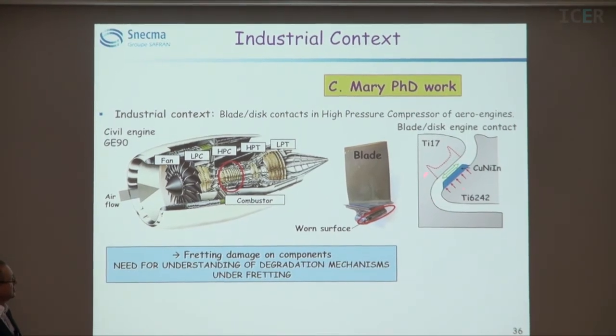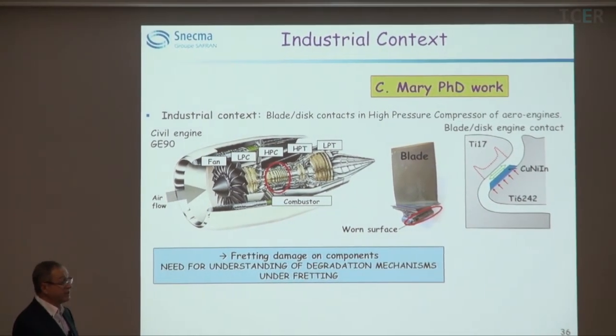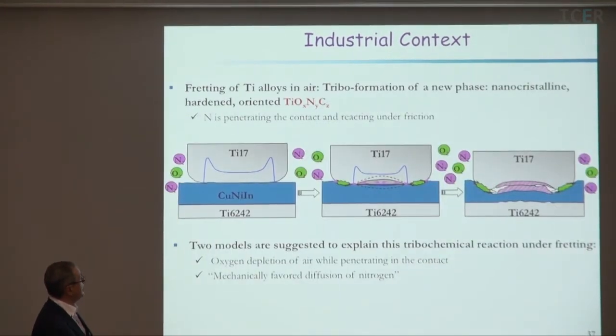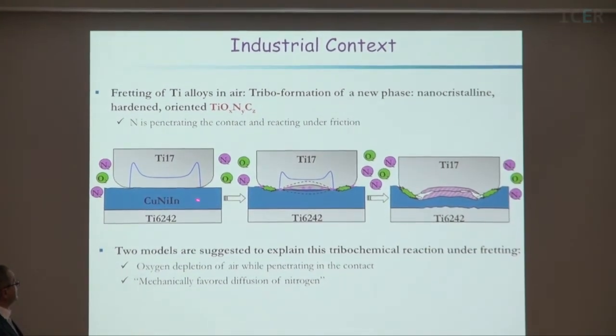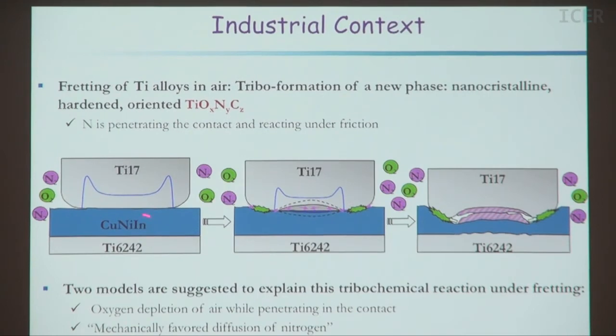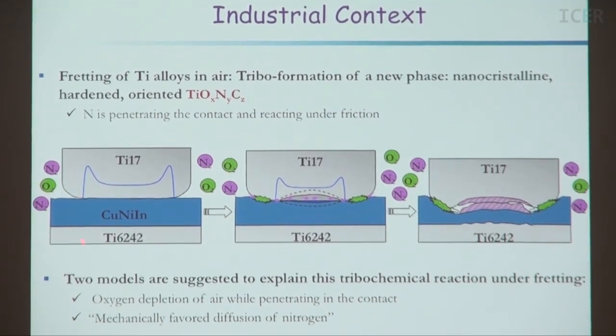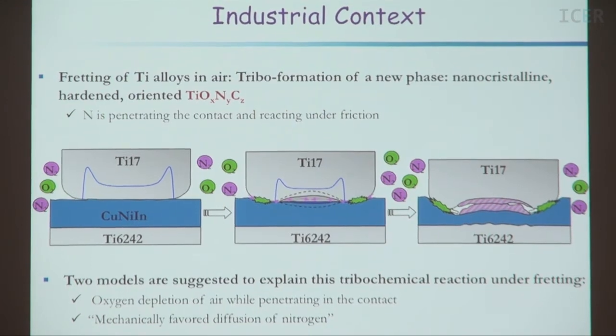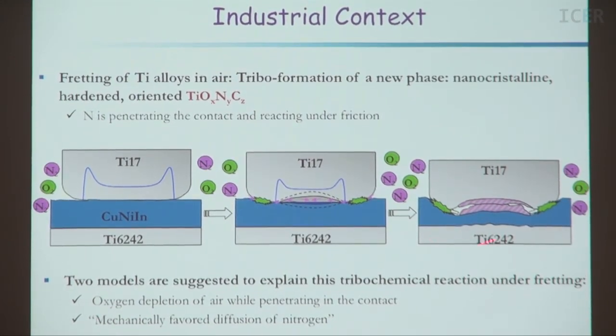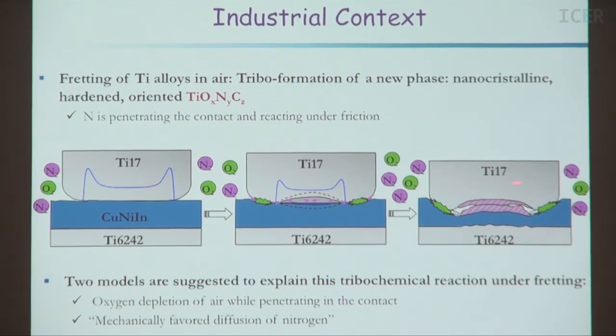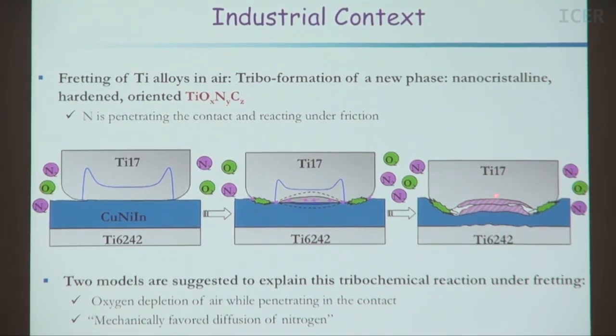So this is working in air, of course, in humid air sometimes. If we look at what happened, typically we are with titanium alloys, and there are coatings. The coating is complicated, but this is the situation at the beginning, and after a certain number of rotations, you can see that there is some wear here. So this wear, and this wear also in the titanium pieces. So damage, and this damage is very severe.